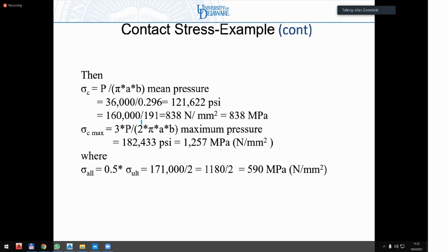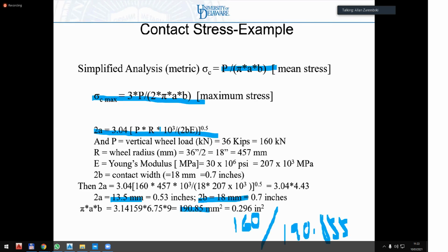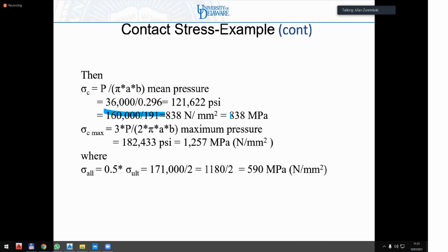So again, 160 over 191 gives me 838 megapascals for my average contact stress. My maximum stress is 1.5 times that, or 1,250. Typically, for most cases, I usually want to keep my stresses below 50% ultimate.